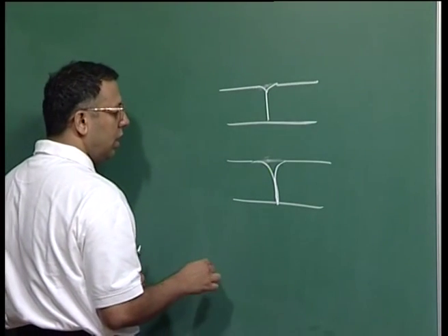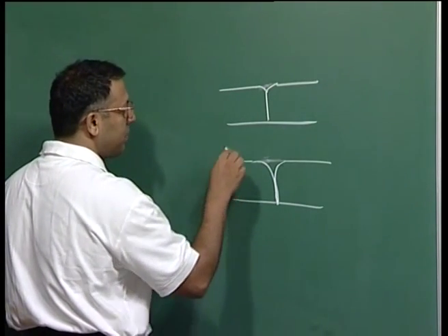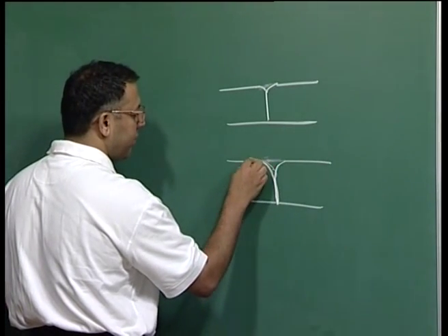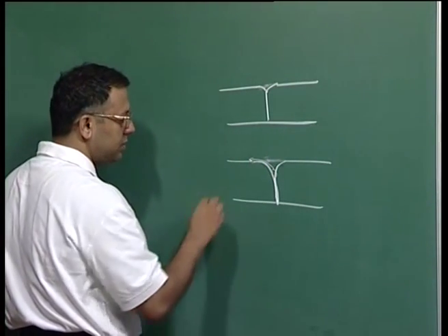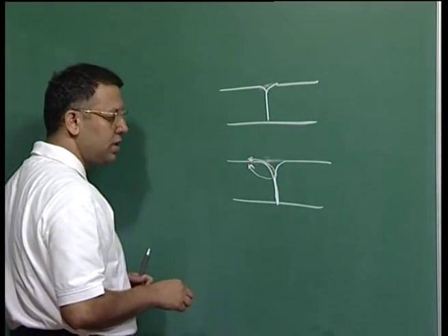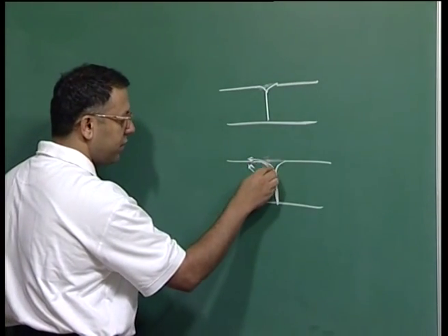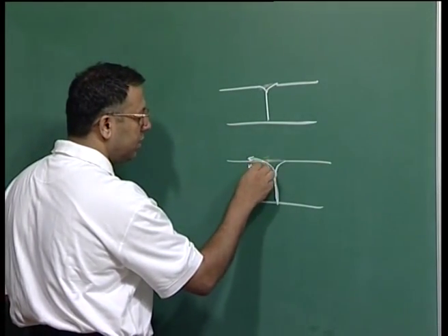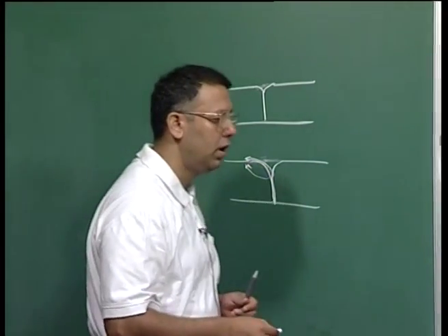Now, in this case, for such a deepening to take place, mass transport has to occur from regions here where there was material to the surface, and this can take place either through the bulk or it can take place through the surface. But essentially it is observed in such problems that it is the surface diffusion which is playing a dominant role, because the diffusivity of the surface, because of the available freedom of the atoms to be present there, is much higher than the bulk diffusion.